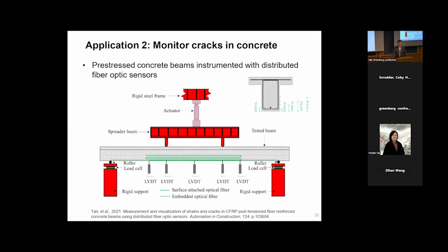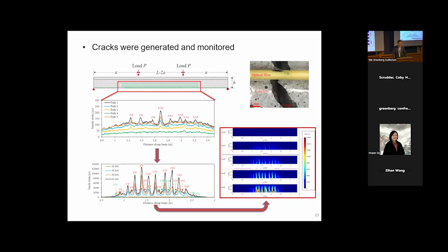Based on the basic materials application, we then apply this sensor technology to structural elements. We tested a pre-stressed concrete beam under 4-point loading, basically bending, and we deployed the sensors at different depths of this beam, as shown by the green lines. When we increase the load level, we can detect peaks. Each peak represents a crack. As you can see, when we increase the load from 30 to 61 kilonewton, we saw more and more peaks, and the magnitude of the peaks also increased. This means we detected the cracks, and we were able to have real-time monitoring of the cracks.